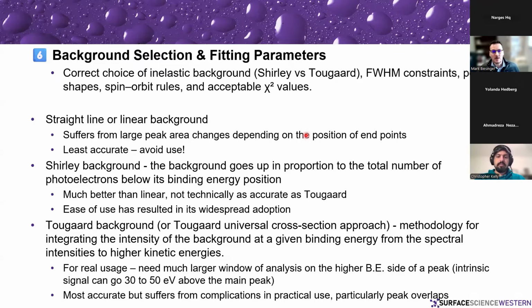For a straight line or linear background, one problem is that you can get large peak area changes depending on the position of the endpoints. If you have a starting baseline endpoint down here and an ending baseline endpoint up here, as you change the positioning of that background you get huge area changes depending on where the endpoints are. So it's not very accurate unless you have a basically straight background that starts here and ends here. I would avoid using a linear background for all but maybe the most